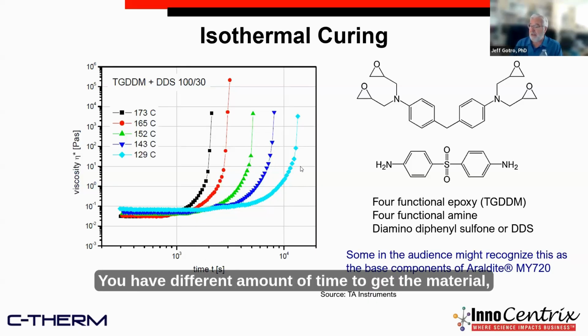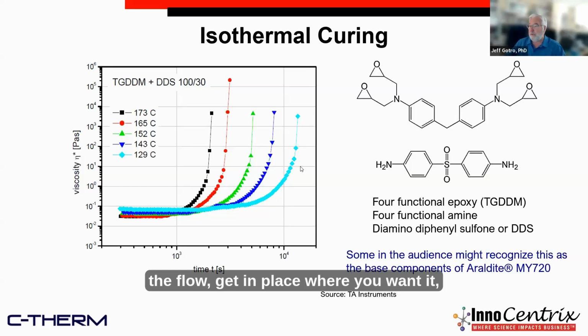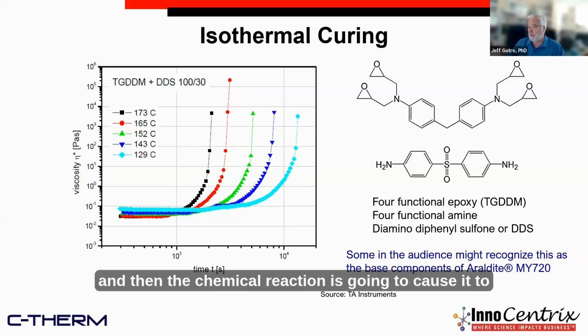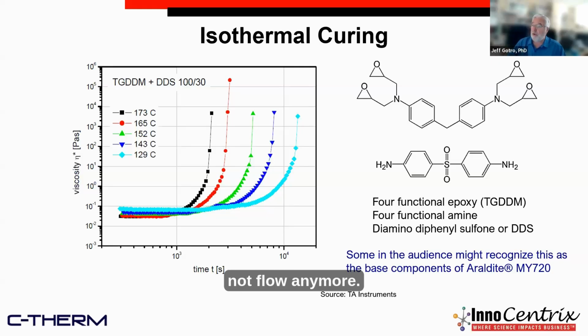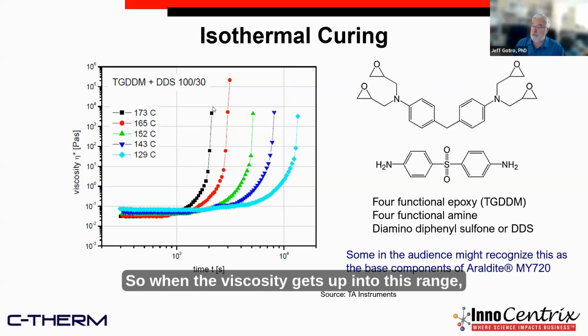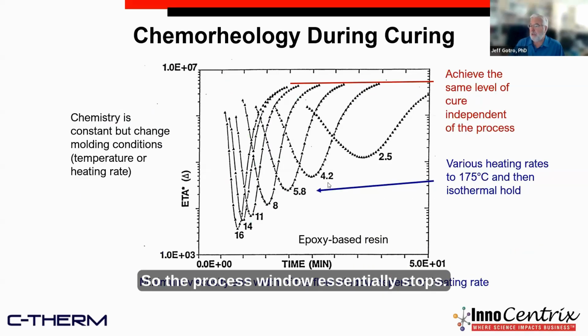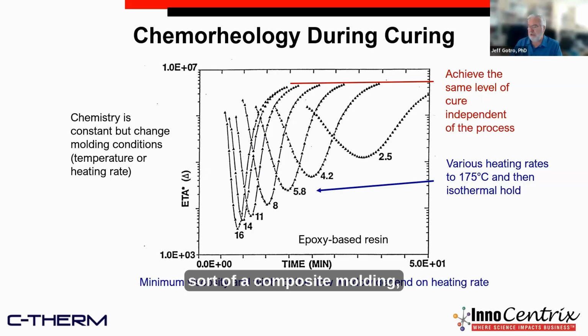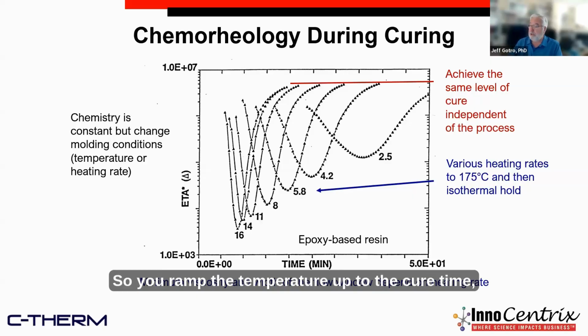You have a different amount of time to get the material to flow, get in place where you want it, and then the chemical reaction is going to cause it to not flow anymore. So when the viscosity gets up into this range, where these curves essentially go vertical, you're not going to get any more flow. So the process window essentially stops. Then if you do it non-isothermally, i.e. you're in a press or some sort of composite molding, you can ramp the temperature up to the cure temperature.